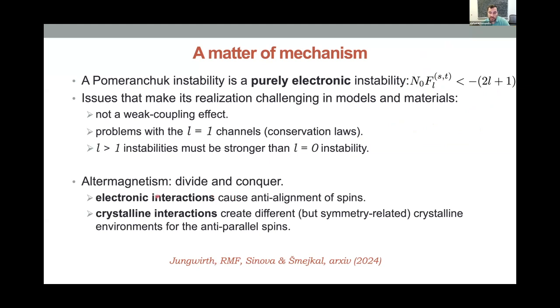So you let electron interactions do one part of the job, which is making the spins anti-align, roughly. And you let the crystalline interactions do the rest of the job by creating different but symmetry-related crystalline environments for these anti-parallel spins. So it is both of these interactions acting together that enables altermagnetism. And I want to show an explicit example, so you see how this happens and why it matters for the sizes of spin splittings that we're looking for.